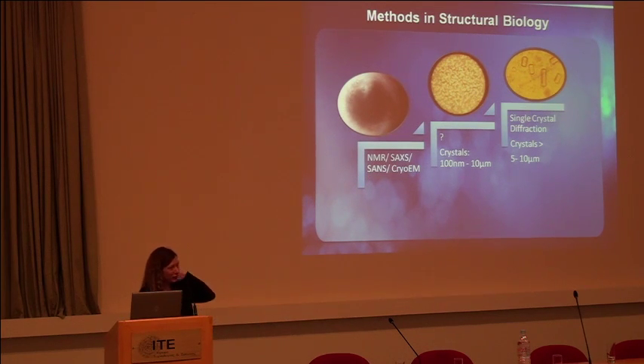When I started working in this field back in 2003, we saw that there is a methodological gap, so there was no real method to study samples like this, which are so often obtained in your lab during crystallization screens. So the question was whether we could apply the powder diffraction technique in order to solve and refine protein structures from crystals of these sizes, from 100 nanometers to 10 microns.